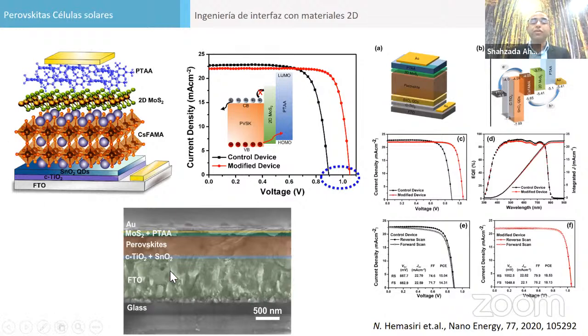This is a cross-sectional SEM image of the devices. You see the tin oxide is a very thin layer, 100 nanometers, and the perovskite is 400 nanometers. MoS2 and PTAA are almost close; we cannot see the MoS2 because it is only a very thin layer, 1 to 10 nanometers, and PTAA is 50 to 60 nanometers. This is the cross-section of the devices.